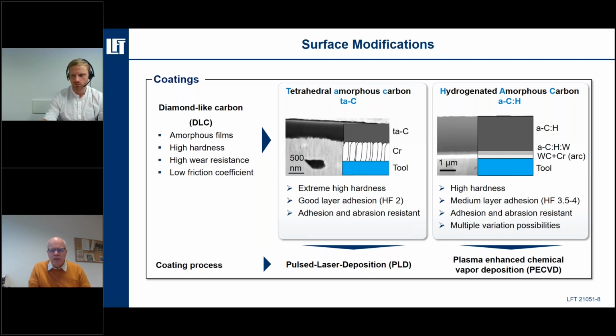The one is the pulsed laser deposition, which is, so to say, similar to an additive process. You have a laser and you have a material and you apply it to the surface. We result in extremely high hardness here, and we have a very good layer adhesion, which means the coating is not that easily removed from the original tool, and adhesion and abrasion resistance is very high. However, this process is slow and might have some limitations regarding the reachable geometry, because somehow you have to get there to apply the laser pulses.